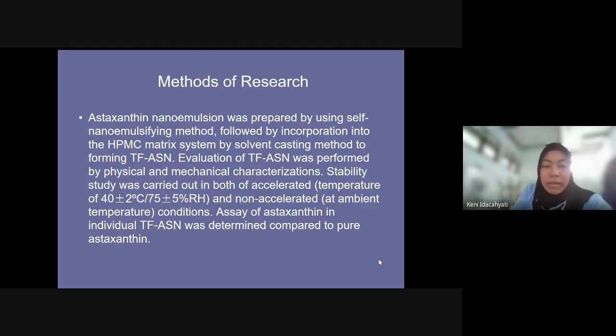Method of research: the general method is that astaxanthin nanoemulsion was prepared using the SNEDDS method, followed by incorporation into the HPMC film-forming system by the solvent casting method to form the astaxanthin thin film. The evaluation of the astaxanthin thin film was performed by physical and mechanical characterization. The stability study was carried out in both accelerated conditions, at a temperature of 40 plus minus 2 degrees Celsius and 75 plus minus 5% RH, and non-accelerated, at ambient temperature. Assay of astaxanthin in the individual thin film was determined compared to pure astaxanthin.